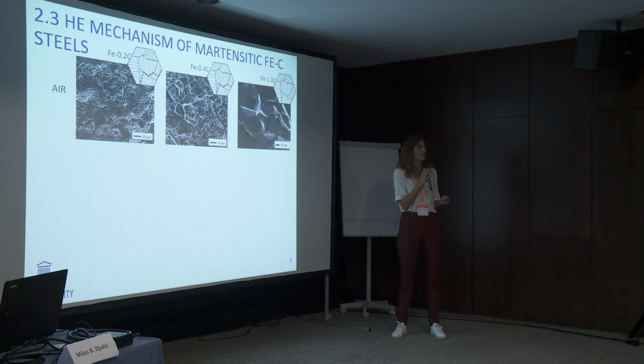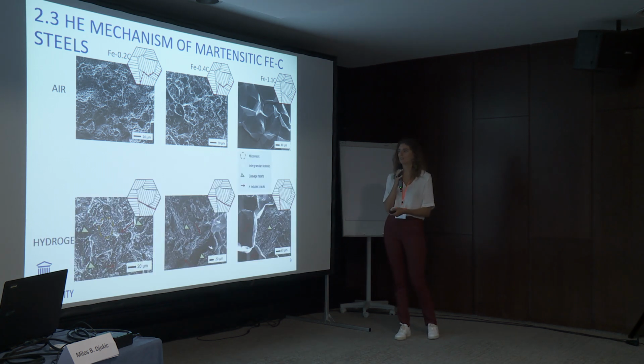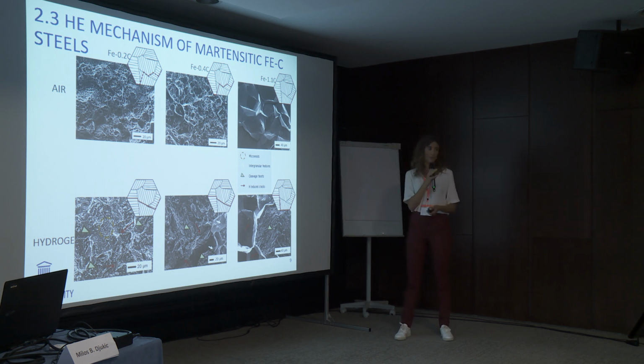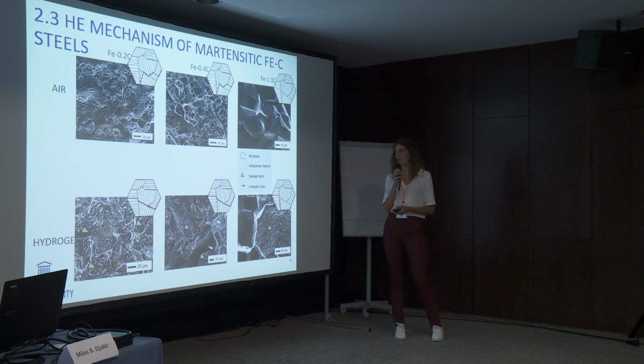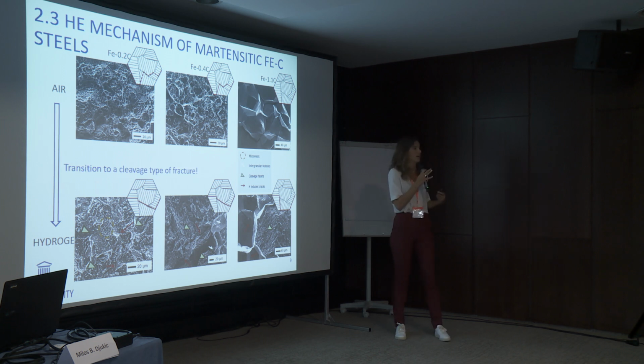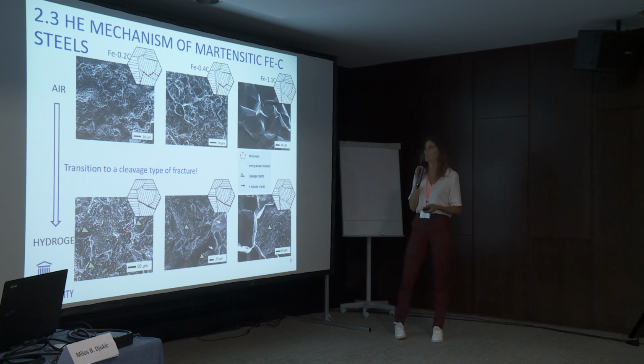Now, it's interesting what happens when we charge these with hydrogen, we saturate them, and then do the bending testing in situ. Well, what we see for all three materials, although they had a very different behavior in air, is that they all have a transition to a cleavage type of fracture. So we can state for these simplified iron-carbon steels that hydrogen causes a transition to a cleavage type of fracture. So hydrogen embrittles in a specific way for all these three types of steel, independent of the carbon content.